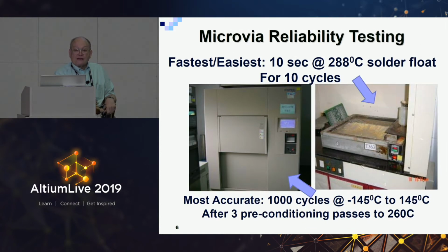And for reliability, I recommend a simple 288 solder pot float, where you take that daisy chain and you float it for 10 seconds, 10 times on this solder pot. So you take that thing, you drop it 10 seconds, pick it up, let it cool, drop it. And you do that 10 times, and you check that you're within the upper and lower control limit on the 4-wire resistance of those 200 or so microvias that are in a daisy chain. And the most accurate one is to have it thermal cycled, minus 145 to 145, after 3 preconditioning passes of 260 Celsius. The 10-second one is one that the operators can do. The other one is more what quality assurance does, the 1,000 cycles type of thing.